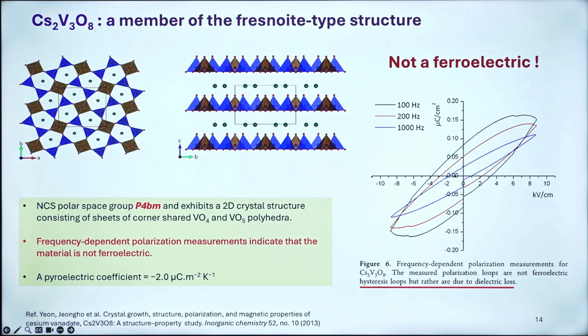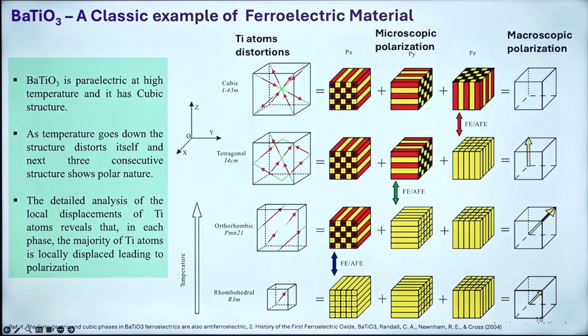So now the next one is Sivaram's thing. You take barium titanate, which is an MSc level solid state experiment which we all do. It's paraelectric at high temperature and it is a cubic structure, which is very simple. Then try to lower the temperature from room temperature. There is a cubic to tetragonal, then to orthorhombic, then to rhombohedral transformation, and obviously there is a distortion in the titanium atom. Okay, so that is the key player.